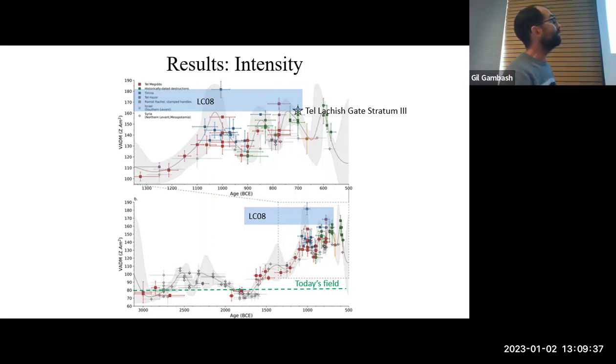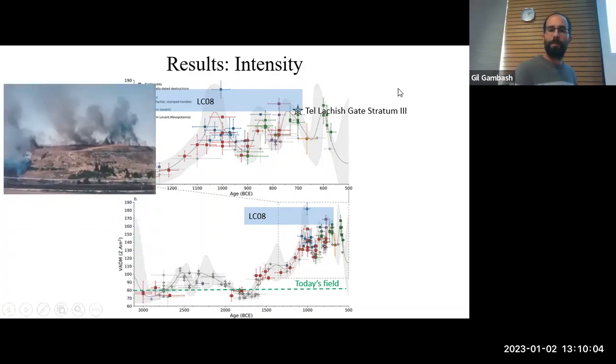And I think it's very clear also from the archaeology there and the finds below the wall that this wall was burnt in 701 BCE. This is the intensity of 701 in Lachish, in the gate area. You see a good agreement. This LC08 seems slightly even higher magnetic field than in the gate area, but there is an overlap of the error bars, so there's no problem. It's very good correlation with 701 BCE.